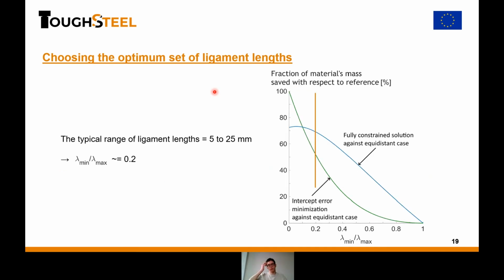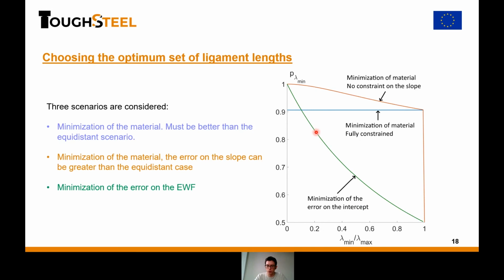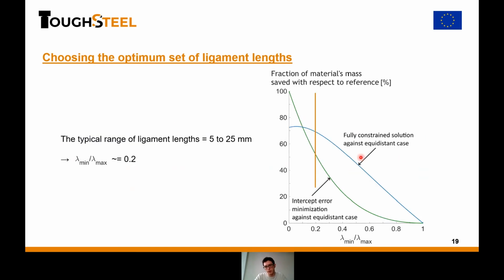What does it translate to in the fraction of material that is saved? So I compare the orange and the green scenarios to the equidistant case. So the fully constrained, we see. I will take again the case that is close to what I work with, which is around 0.2. When you compare the fully constrained solution against the equidistant case, we see that we save about 70% material. And for just the minimization of the essential work of fracture, we save about 50% of the material.